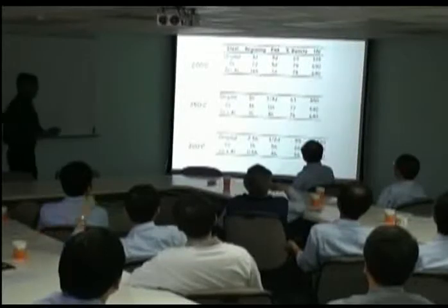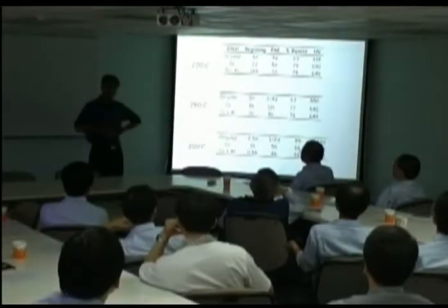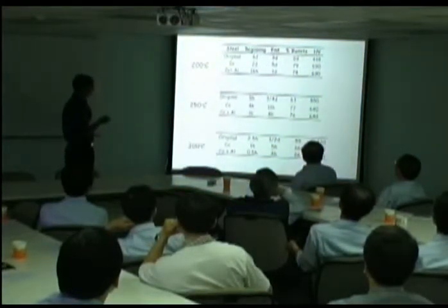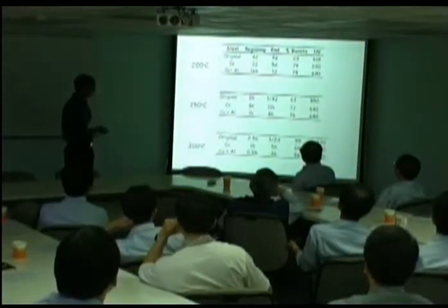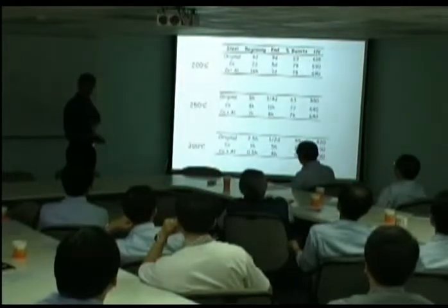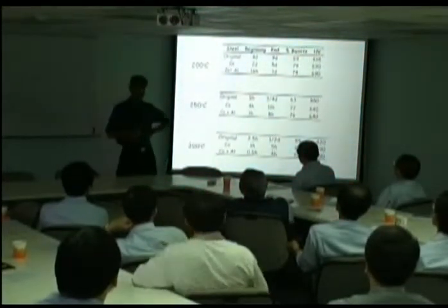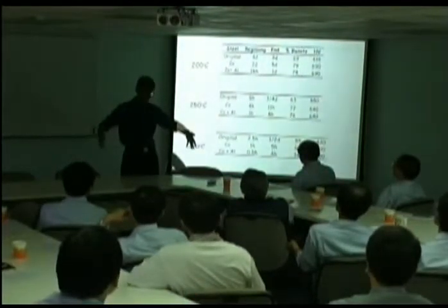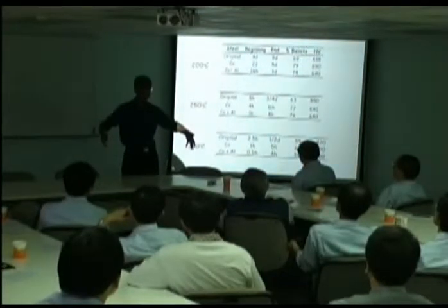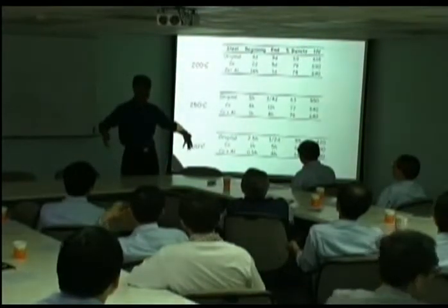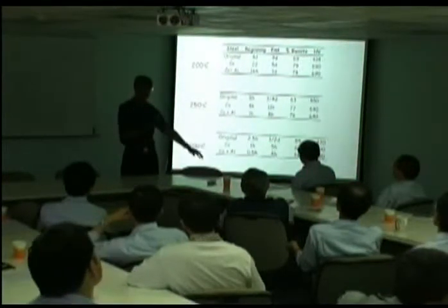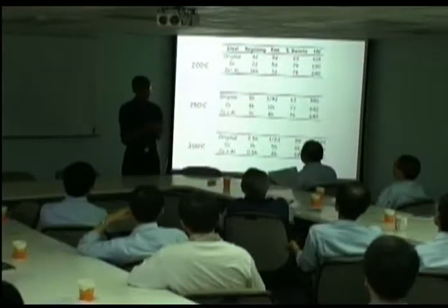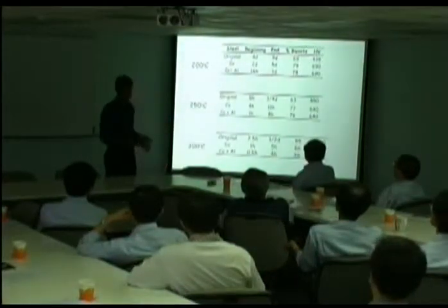Now, we've added about 2 weight percent of cobalt or 2 weight percent of aluminium, and you can see that the transformation time goes down from days to hours. My own opinion is that a slow transformation is a good thing. Because you have a large lump of material, it will reach a homogeneous temperature before transformation starts, so you have no problems about residual stresses and so forth. Of course, if you're making a small component, then maybe you want a faster transformation.